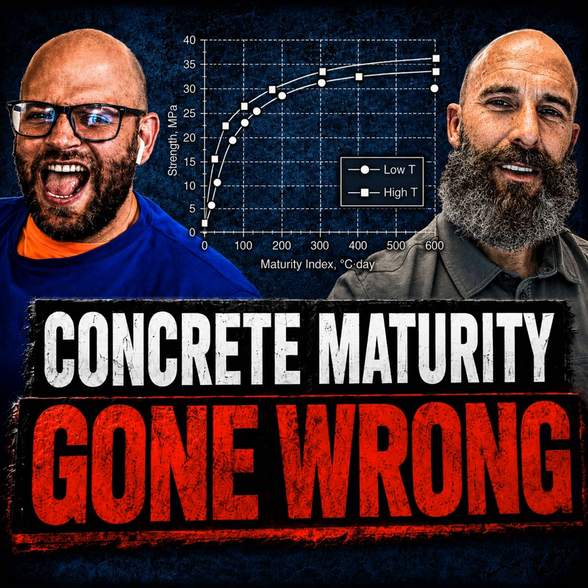Cool? Got it. Okay. So when I say ASTM is amazing, there are some awesome quotes in it. And again, I used to have the privilege and the pleasure of working with Nicholas J. Carino at ASTM. And not only is he a great author, he is a humble editor who devotes a crap load of time. So in the middle section of ASTM C1074, it says, for the datum temperature, for a type 1 cement without admixtures in a curing temperature range from 0 to 40 degrees Celsius, the recommended datum temperature is 0 degrees Celsius.